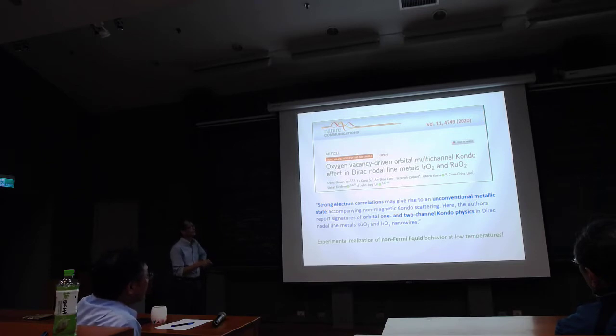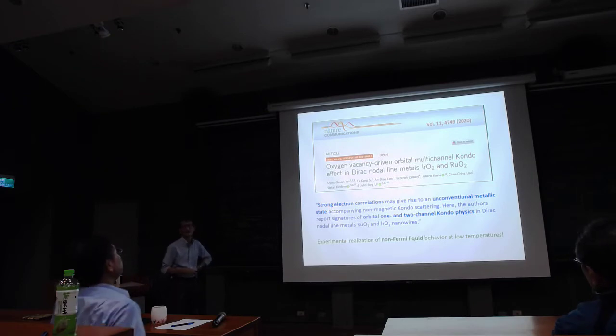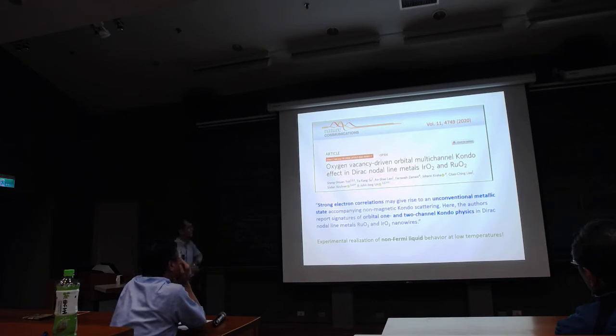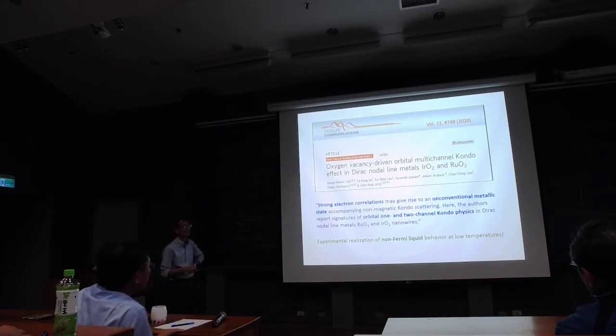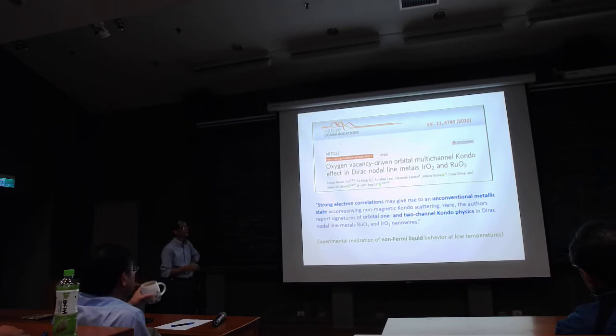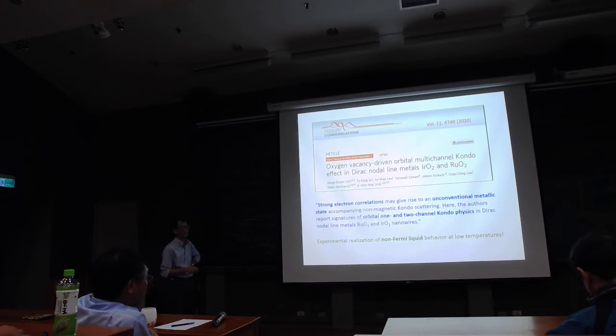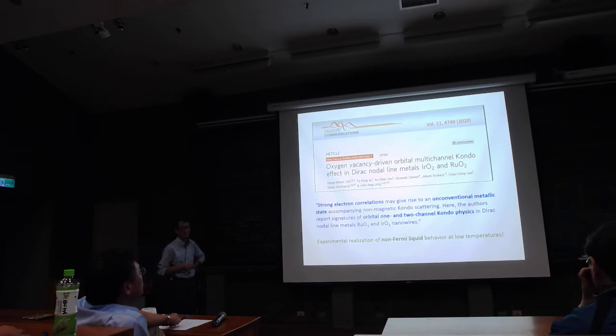And so here is oxygen. In real material, we can have oxygen vacancies. And in this system, we will observe some strong electron correlation effects. And that will give you some non-Fermi liquid state, and we'll call it an unconventional metallic state. And this unconventional metallic state we actually infer from the observation of the Kondo effect, one channel and two channel and orbital. So this is a non-magnetic Kondo effect. This is basically what I want to discuss today. So the ground state is a non-Fermi liquid ground state.